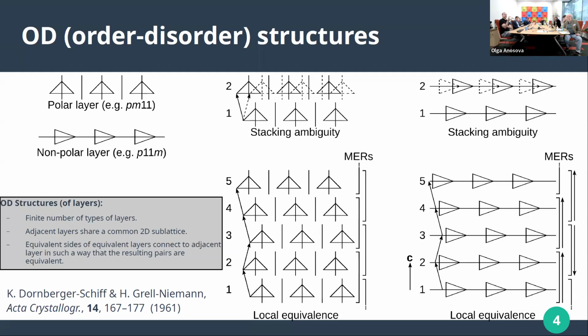Now, when you apply the reflection of the lower layer to the pair of layers, then what happens? The lower layer is mapped onto itself, and the upper layer is mapped somewhere differently. That means you have generated a new pair, and the new pair has the same interatomic distances, obviously, because a reflection is an isometry. But the second layer is located at a different position.